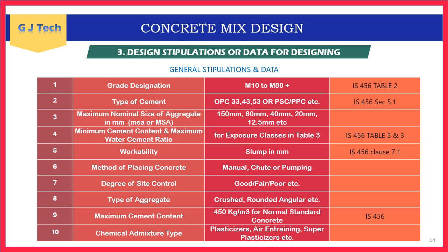Nominal maximum size of aggregates in mm must be specified. Minimum cement content and maximum water-cement ratio are used for checking the computed values — these are provided in IS 456 Table 5 depending on exposure class from Table 3. Workability requirements, such as maximum slump (e.g., 75 mm or 120 mm), are also specified or referred from IS 456 clause 7.1.